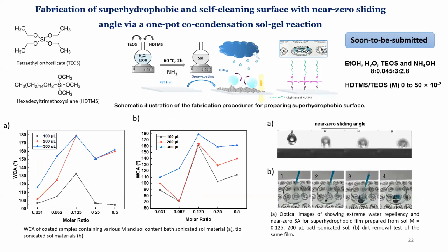And here's what I did back in the lab. I chose tetraethyl orthosilicate and hexadecyltrimethoxysilane. The structures are shown on the top left. The long chain of HDTMS was in charge of hydrophobization. They were added simultaneously to water and ethanol. After 15 minutes, ammonia was added as the catalyst. It was stirred at 60 degrees for 2 hours, and we got our sol.